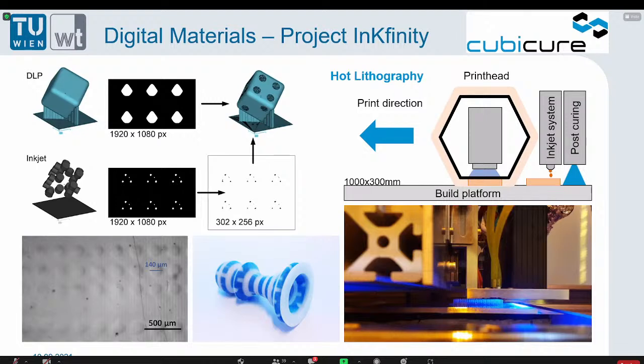And we are now able to produce large parts, which can be modified by inkjet printing, and very many parts at once. It also enables things like curing the ink afterwards, which has not been possible in the former versions of the hybrid printing. And what is even more possible is to process, let's say, difficult materials. So high-viscosity materials and highly filled materials, for example, as you can see on the bottom here on the page, which is an artificial ivory structure, which has been colored. So with this new system, a lot of things are possible, and I'm really looking forward to what can be done in the next months and in the next time. And if you're interested, please watch my talk again.